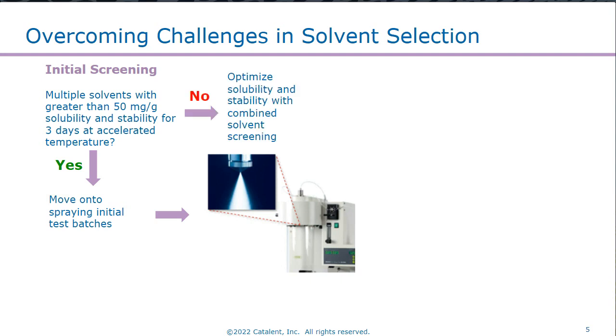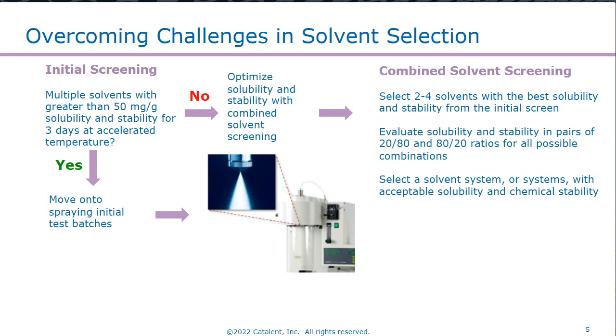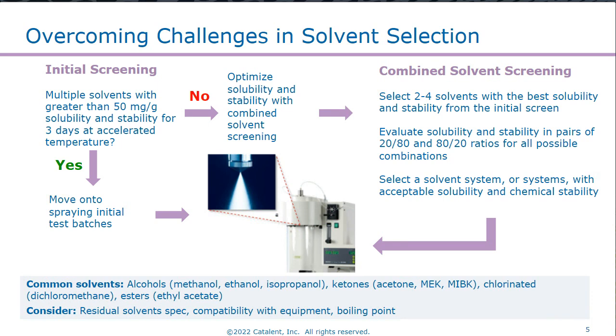If we're not able to achieve that solubility with single solvents, then we'll be looking to optimize the solubility of the API, potentially through the use of combined solvents. So from the initial screening, we'll look at a few of the solvents that are showing the best promise, and start to look at combinations of those solvents, potentially 80-20, 20-80 ratios. And then when we find a system that does have acceptable solubility, we can then proceed with the initial spray drying.